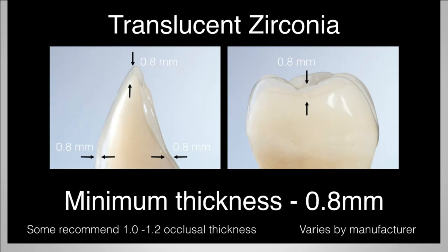In terms of preparation design, manufacturers today report that you can get down to about 0.8 millimeters in occlusal thickness. Now that number, I am concerned about it. While this is theoretically possible, my concern is when we go to try this restoration into the patient's mouth, if there's any occlusal adjustment that needs to be done to the restoration, we've now thinned below 0.8 of a millimeter. Once we drop below 0.8 of a millimeter in thickness with translucent materials, we start to lose their strength. In terms of traditional zirconias, once we drop below 0.5 millimeters, we lose our strength. So I don't like to operate in these ultra-thin worlds.